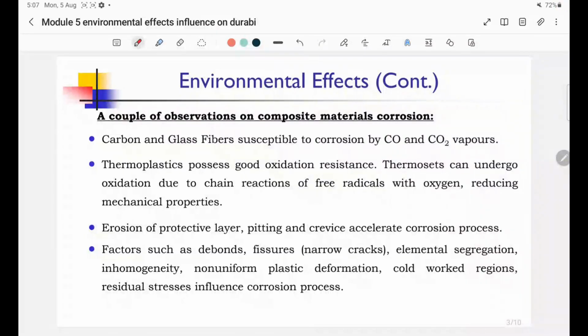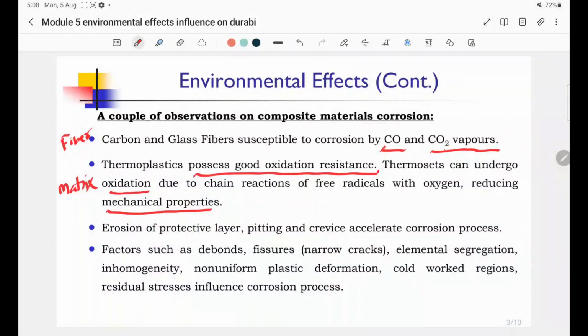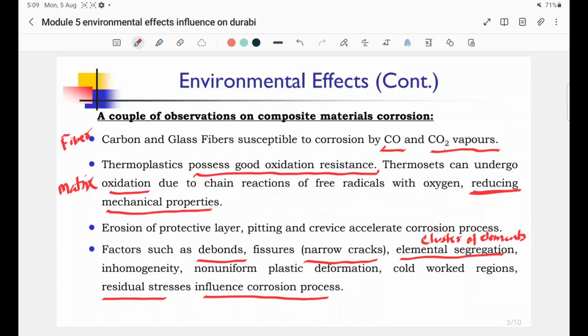Some of the important observations made on composite material corrosion. First we will see the fiber: carbon fiber and glass fiber undergo corrosion when in contact with carbon monoxide and carbon dioxide vapor. Coming to the corrosion of the matrix material, thermoplastic exhibits good oxidation or corrosion resistance, whereas thermoset undergoes corrosion. As a result, the mechanical property of the thermoset composite gets reduced. The factors such as fiber matrix debonding, narrow crack formation, plastic deformation, a cluster of elements known as segregation of elements, and residual stress are the main factors that influence the corrosion process.